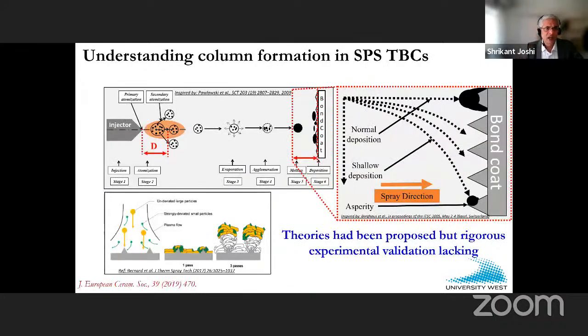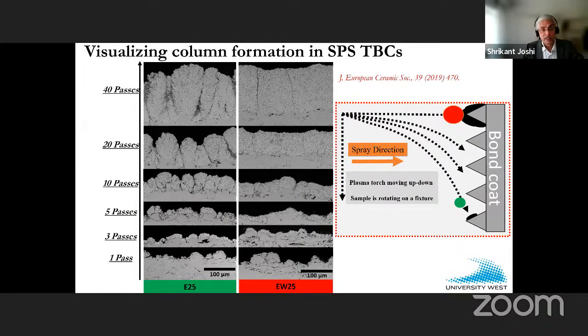And we also spend a lot of time trying to understand column formation. When do you get columns? When do you not get columns? There were, of course, theories which had been proposed, very logical ones, of course, but we spent a fair bit of time to validate experimentally the fact that we can indeed engineer columns or avoid them completely. For example, these are illustrations of how the coating buildup occurs when you use ethanol or ethanol water mixture, or what I'm not showing here is if you used water, you get entirely different